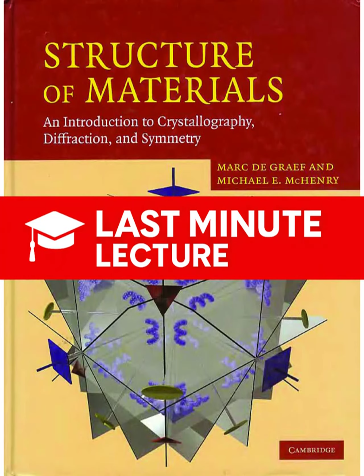This systematic analysis of symmetry and its consequences leads us directly to a really fundamental constraint in the entire field of crystallography, which is Friedel's law. Yes. Friedel's law is a bit of a tricky one. It states that the entire set of measured diffraction intensities, I_HKL, will always display a center of symmetry, even if the actual crystal structure does not possess one. So the pattern of dots looks symmetric, even if the thing that made it isn't. That's a good way to put it. In other words, the intensity of the HKL reflection is always equal to the intensity of the inverse reflection, the H bar, K bar, L bar reflection.